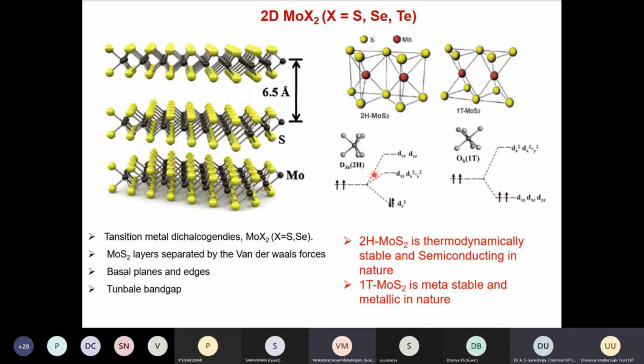In any synthesis which you do, mostly you end up in a 2H phase, which is semiconducting in nature, but the activity of the 2H is very low compared to the 1T phase. The 1T phase is more metallic, so more conducting, and the activity is better. However, stabilizing 1T is very challenging. It's not very easy. Even if you prepare it, it always exists together with the 2H phase. So what I say in the rest of the talk as 1T means it has some contribution from 2H as well,